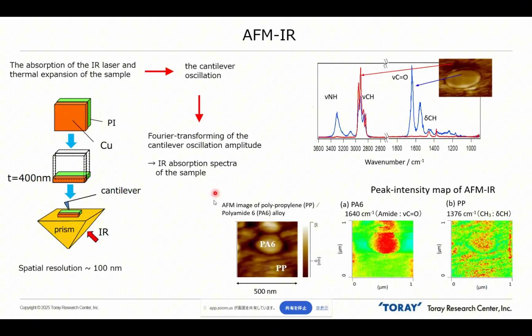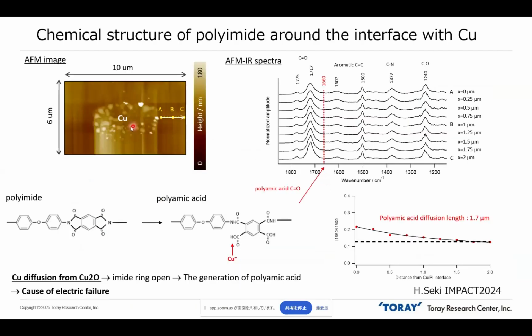On the right side, in this example, the sample is a phase-separated polymer alloy, with phases on the order of 200 nanometers. These IR spectra can resolve the two phases very clearly. So we try to use this technique to get sequential spectra using the same sample, the copper and polyimide interface.